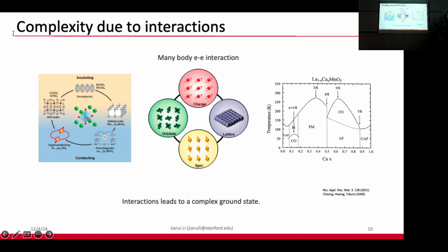For example, in this lanthanum calcium manganite, the lanthanum and calcium concentrations can be continuously varied from 0 to 1, and that gives us the freedom to control the electron-electron interactions in the charge, spin, orbital, lattice degrees of freedom in this compound, which leads to a lot of very interesting electronic ground states in the material. And by doing this, people have realized a lot of macroscopic functional phases, such as superconductivity, ferromagnetism, or ferroelectricity.